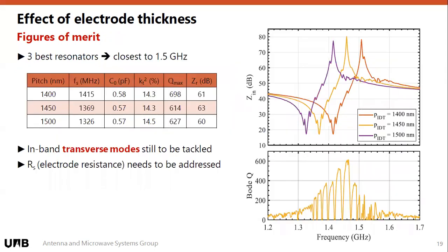So we have achieved a pretty interesting resonator. Maybe it doesn't seem like the best resonator, but if you consider that we're playing with mechanical waves on a thin substrate that has to be excited with IDTs, this was for us an amazing result. And we analyzed these three best resonators. These are the ones closest to the working frequency of our structure, so closest to the 1.5 gigahertz at which the silicon oxide layer was providing this isolation from the substrate.